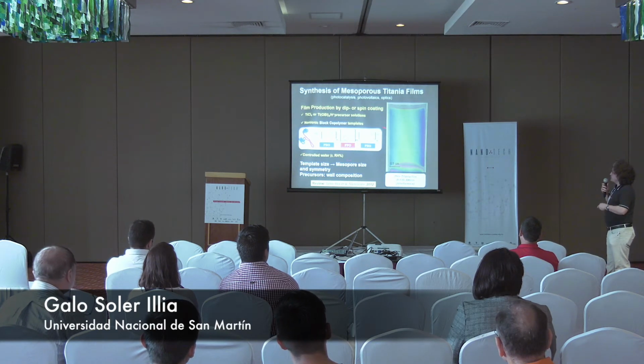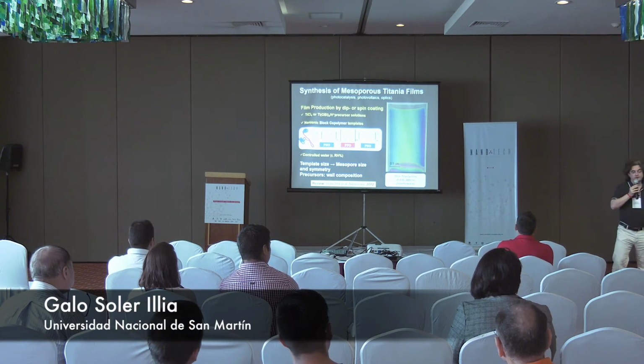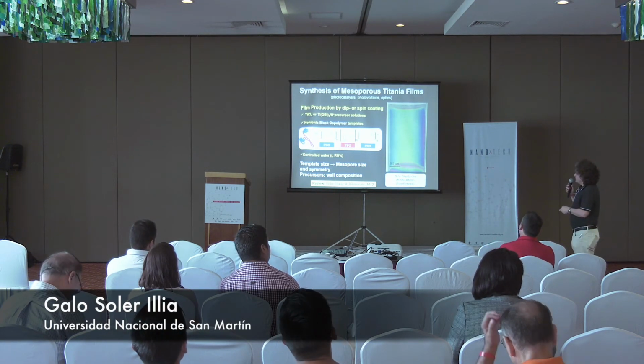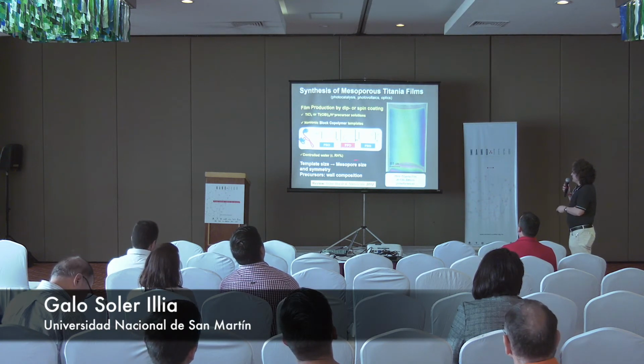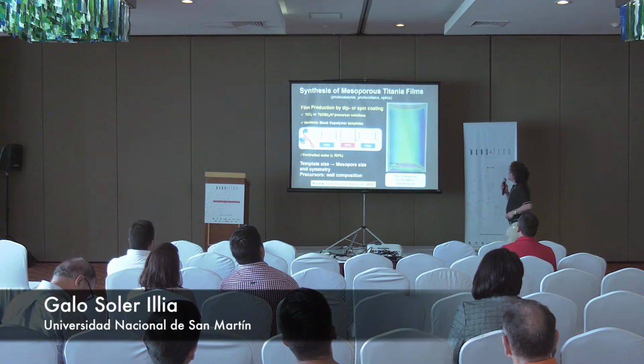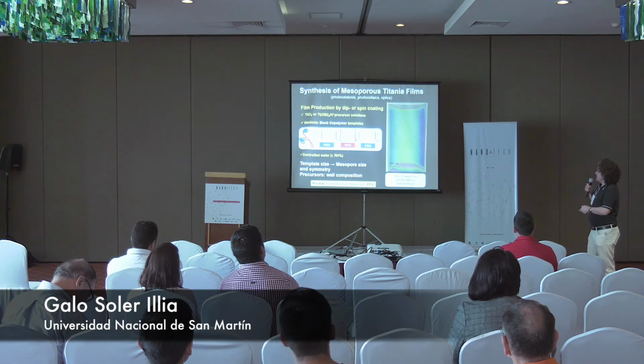Then we use surfactant. This surfactant is particular, it's a polymeric surfactant, a non-ionic block copolymer. It's a polymer with 3 blocks: hydrophilic, hydrophobic, hydrophilic. It can be tailored by tuning this, and can be bought from several providers. And by changing the N, this is very nice, it was discovered by several researchers, Wiesner and Stucky groups, 20 years